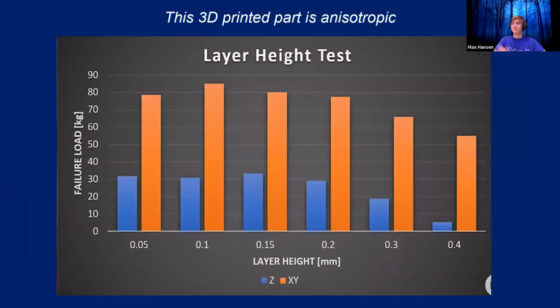And then this, I believe, is an incredibly important graphic. This is putting the two side by side, and you can see this XY in the orange is leaps and bounds ahead of the Z-axis one in terms of strength, and it drops off less as you get thicker layer height. So this is pretty much one of the most important things you want to focus on when printing. You need to think about which axis you're printing on and which axis the force is coming from.